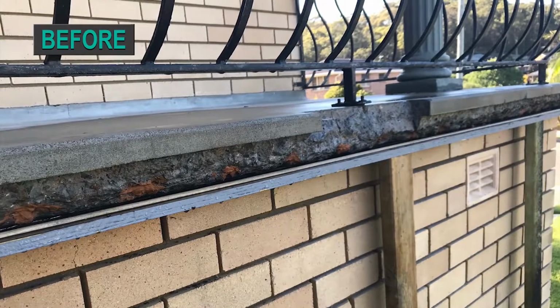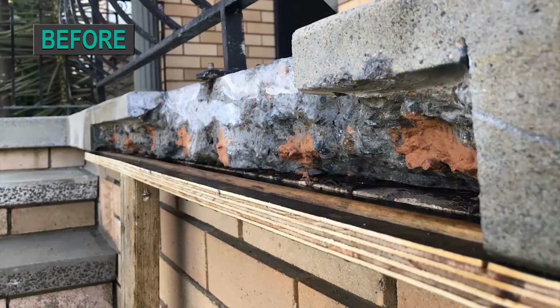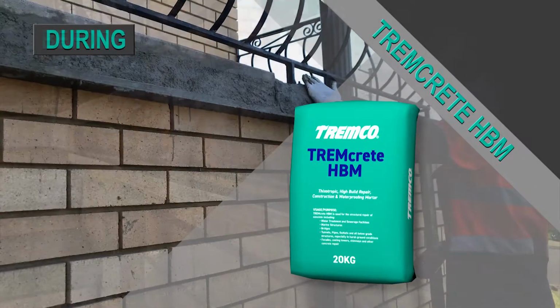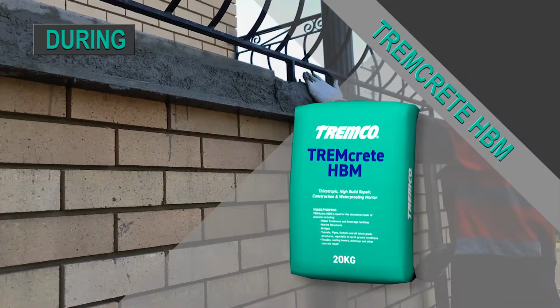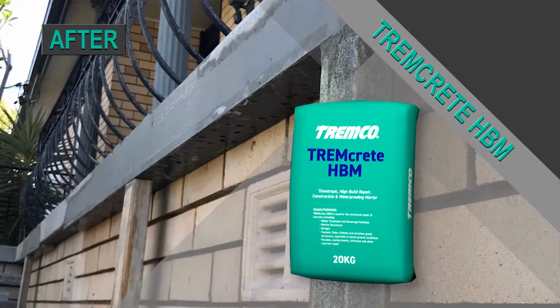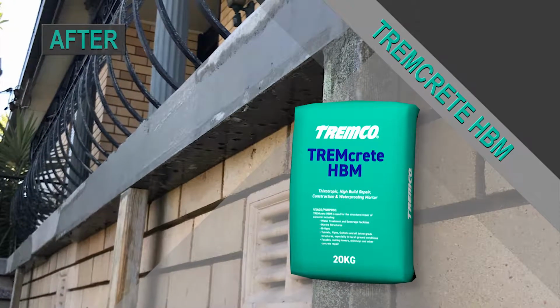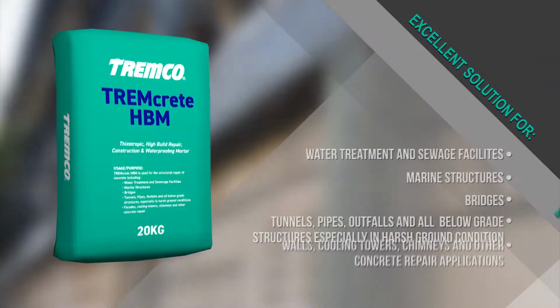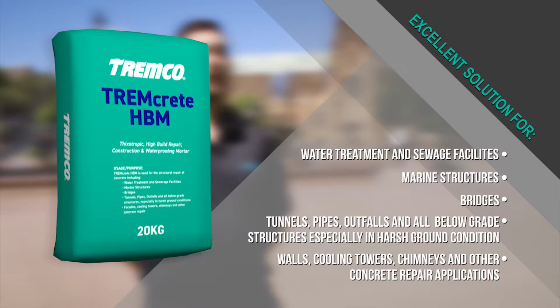The TREMcrete HBM is our high build mortar, has excellent mechanical properties, so a compressive strength of 59.4 MPa. It is shrinkage compensated, so in spalled repairs it's not going to shrink. There's going to be no risk of delamination. It is a really versatile product, so we can use it between 10 and 90 mils, even in overhead applications with no risk of segregation, no risk of sagging.